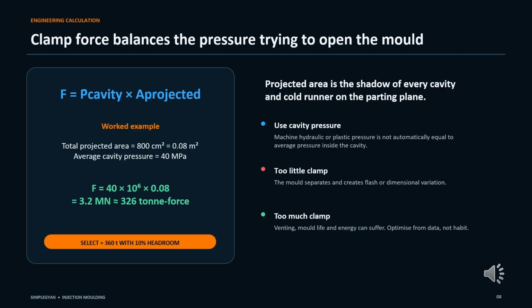During filling and packing, cavity pressure acts across the projected area and tries to separate the mold halves. The basic engineering relation is force equals average cavity pressure multiplied by total projected area. In this worked example, 40 megapascals acting over 800 square centimeters produces 3.2 meganewtons, approximately 326-ton force. Adding 10% headroom suggests a machine near 360 tons. This is an illustrative calculation. RJG advises including the projected area of cold runners and using actual cavity pressure information when available.